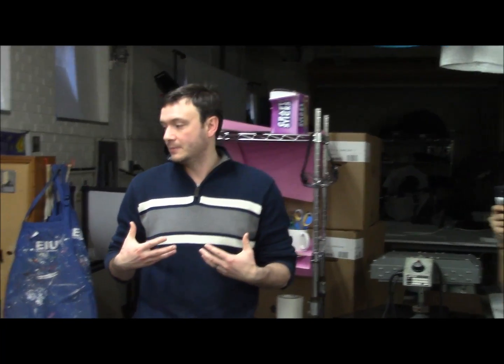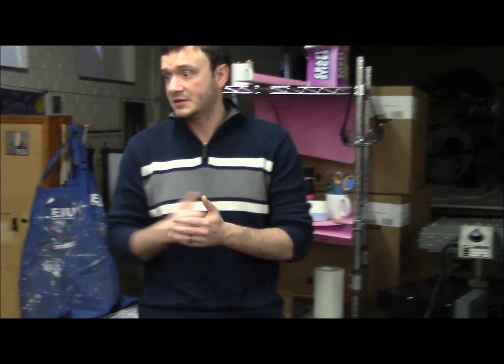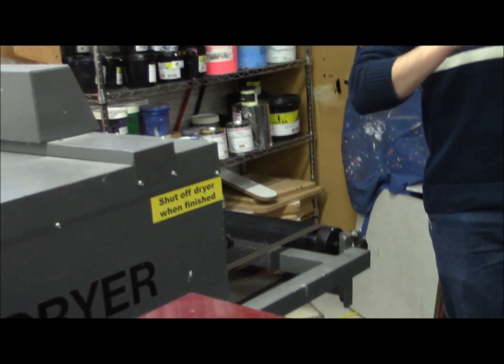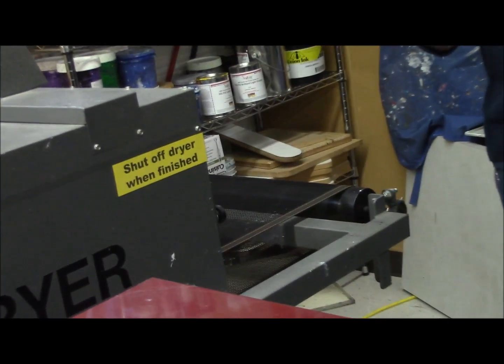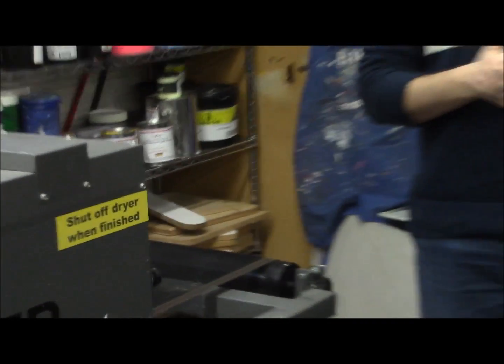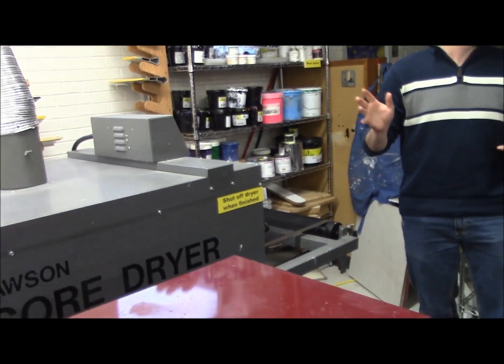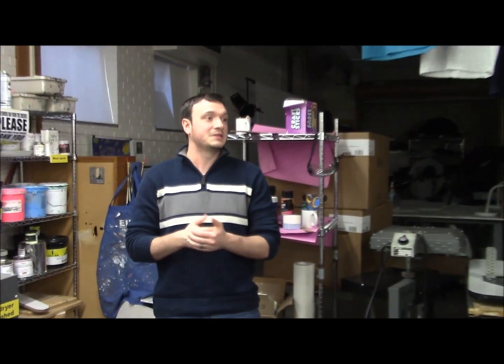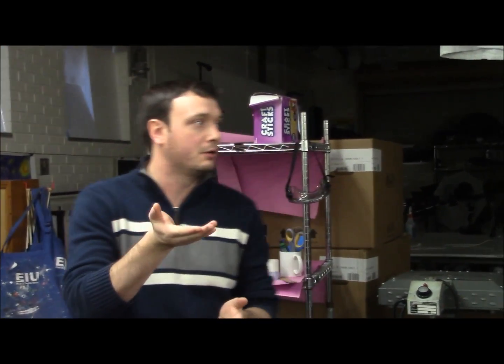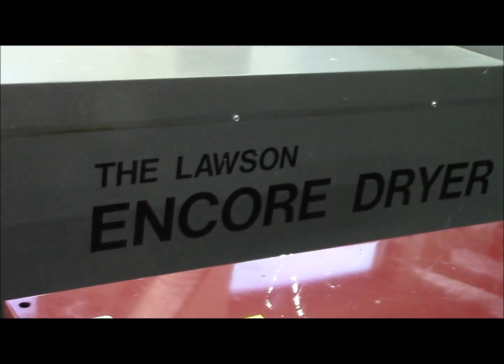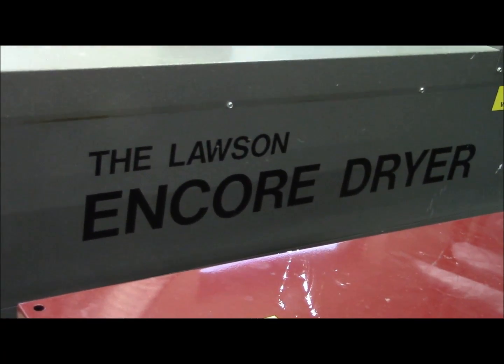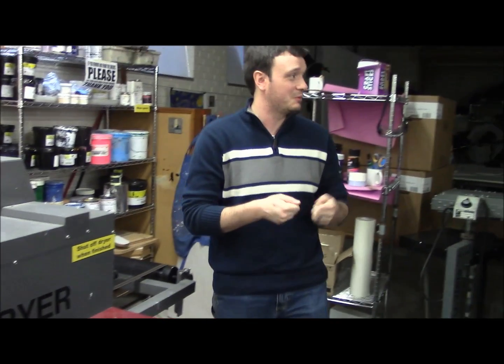And I've seen examples where students who are working on tasks or projects have actually bubbled the ink off the shirt because it was going too slow. Or the other component, having it too hot or too cold, because if the ink does not come up to a temperature of 330 degrees for plastisol, it won't bind to the fabric itself. And you can see part of that whenever you pull it apart, and believe it or not, in some of that research, your hands are the best tool that you have to be able to test it.